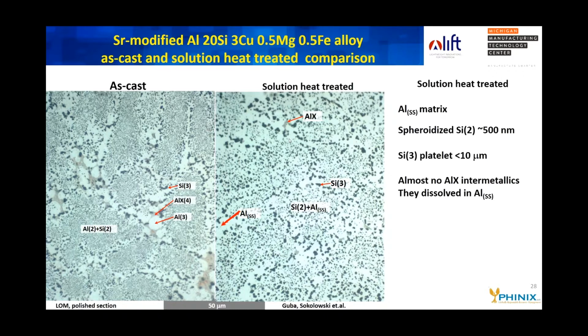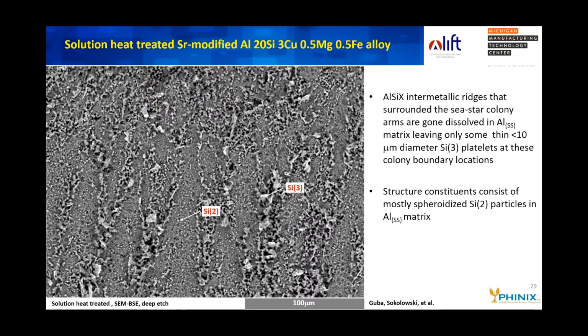The silicon Si2 has coarsened, but it is still mostly about 500 nanometers. The little larger Si3 platelets at the grain boundaries sometimes spheroidize, sometimes stay as platelets, but they're still less than 10 microns, and they're isolated from each other rather than forming networks.